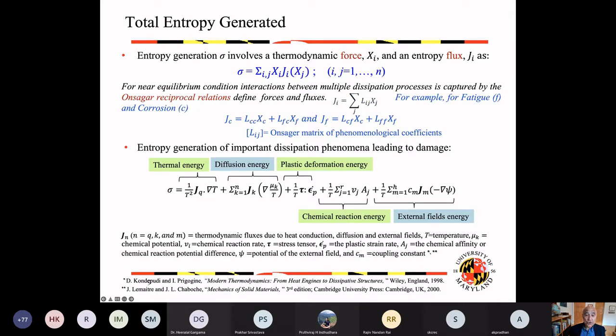So let's say if you have only corrosion fatigue, this matrix is a 2 by 2 matrix of the phenomenological coefficients: corrosion on corrosion, corrosion on fatigue, or fatigue on fatigue. And therefore, each of them can be written in this form. So what is the importance of this? The importance is that when we have a lot of these phenomenological aspects in reliability that interact with each other, such as corrosion fatigue or creep fatigue, then these can be well defined. This has been really a sore point in reliability in the past, because we had difficulty modeling them properly. And now entropy allows us to do that very smoothly and nicely.